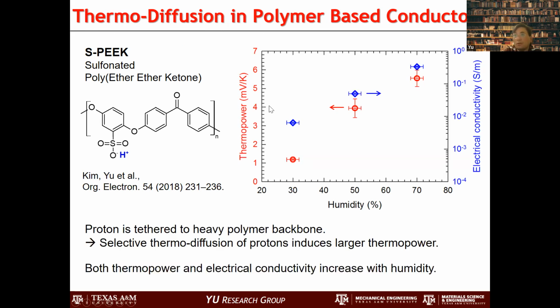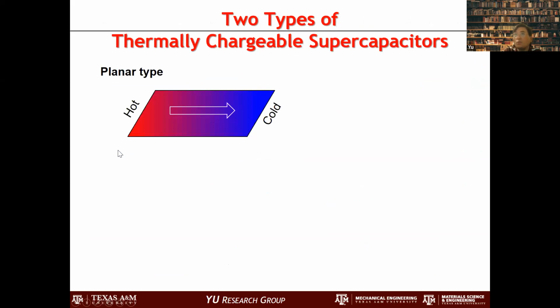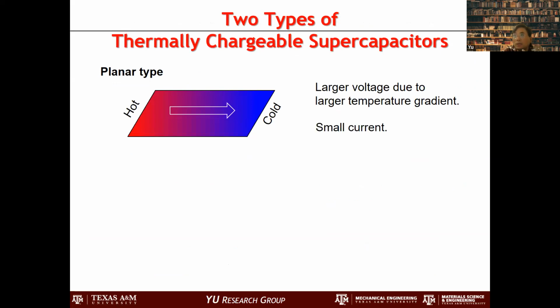So, since it has a pretty large backbone and the backbone doesn't move, but the mobile proton is moving, which is good. And so we developed two different types of this capacitor. One is a planar type, so that we can have a thin film, and we create the temperature difference along this thin film direction, in the in-plane direction.